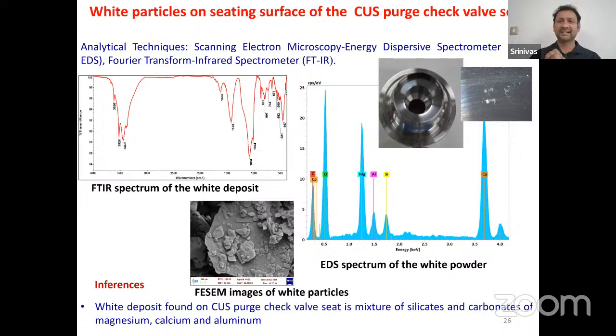So if you see, this is a cryo upper stage, which is used for the GSLV Mark III vehicle, where this cryogenic upper stage was put through a heat trial test. Here on the right side you see some white colored deposits they have found. They want to know the type of deposits from IR and SEM EDS, that is energy dispersive spectroscopy. From IR, around 1000 and 1400, you can find out that it's based on silicates and carbonates.